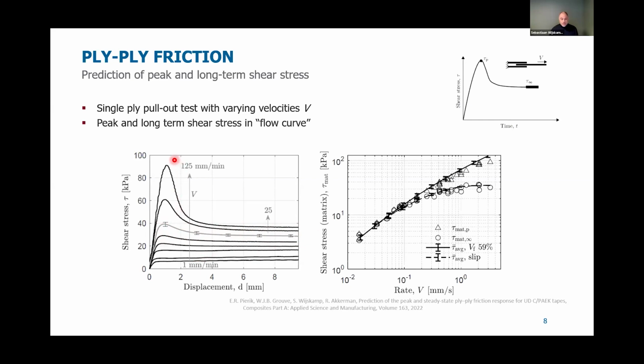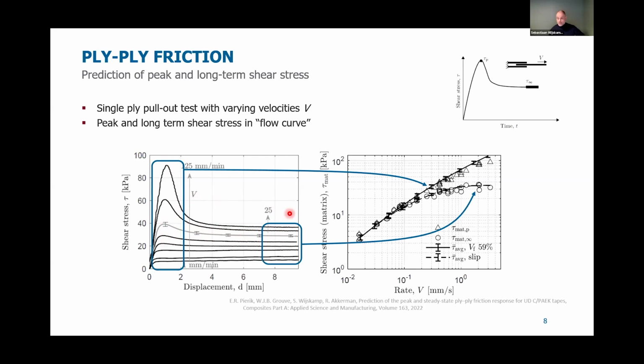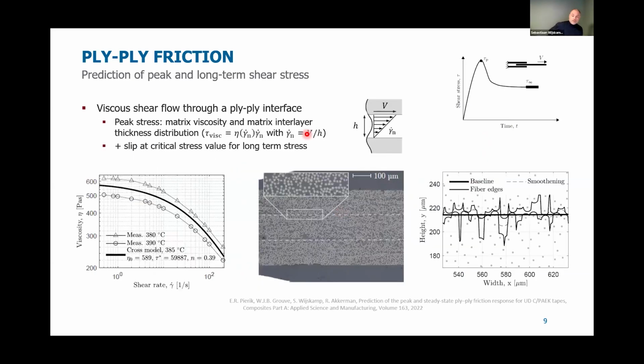And if you take all the peaks and all the long-term shear stresses and plot them on a log-log scale, you can create a so-called flow curve. One of our researchers, Wijskamp, has been able to model this flow curve, both for the peaks and for the long-term shear stress. Here you see that until a certain point, the peak and the long-term shear stress coincide. That means that there is no peak. We see that, for example, at the lower rate here. At a certain point, the long-term shear stress does not grow with the rate, and it reaches some kind of plateau. Well, Wijskamp has been able to model that.